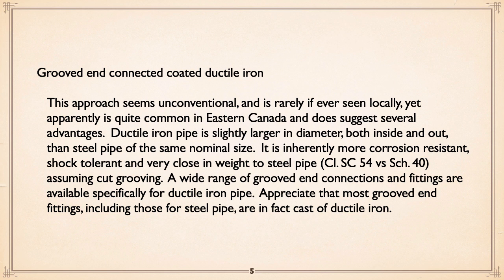Number 5, this is something that I myself have never seen done, but something that I would like to see done someday. You don't see it much locally, and I'm talking Western Canada, but in Eastern Canada, it's quite common. And it suggests several advantages. Ductile iron pipe is slightly larger in diameter, both inside and out, than steel pipes. You get a little better flow for any given size. It inherently is more corrosion resistant, being iron. Shock tolerant, ductile is at normal temperatures comparable to steel and very close in weight to steel pipe. A typical class SC54 versus Sked 40 steel.